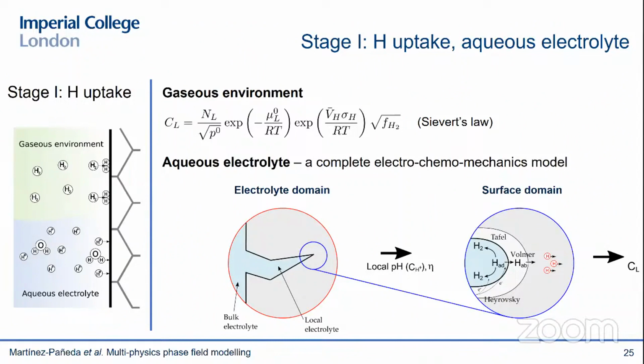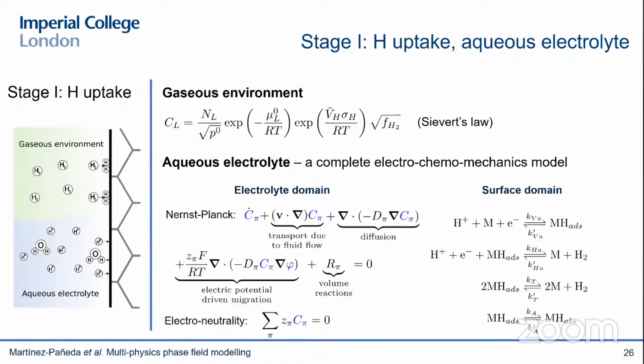The aqueous electrolyte system is much more complicated because you need to resolve all the surface reactions happening in the surface of the metal, and then you also need to solve the electrochemistry of the electrolyte, which can be very different inside of a pit or a crack relative to the bulk. But we do know what are the physics, the equations that govern the hydrogen evolution reaction and the electrochemistry of electrolytes, so we can formulate a theory, and then we can implement that theory into a finite element code.